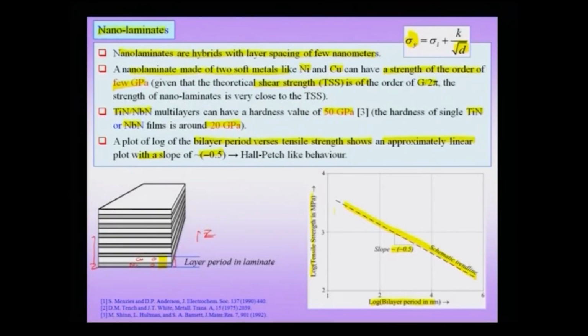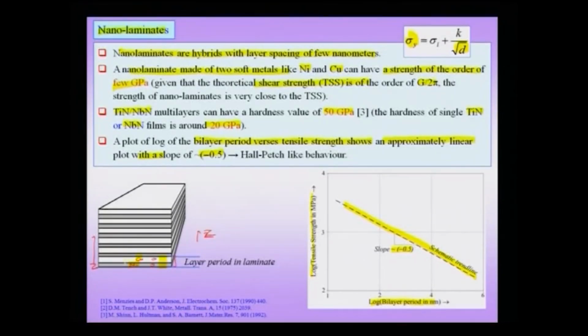To summarize this slide, we can not only have nanoscale materials, but we can have nano hybrids, in which case the two components forming the composite or the hybrid structure are both of the nanoscale. In this case, the individual layers, for instance, of nickel and copper are on the nanoscale, and not only that, this kind of a nano laminate actually shows very high strength, even though it may be made of materials which are actually soft like nickel and copper, and this can approach almost the theoretical shear strength of the material, and that means the yield stress could be of the order of gigapascals.